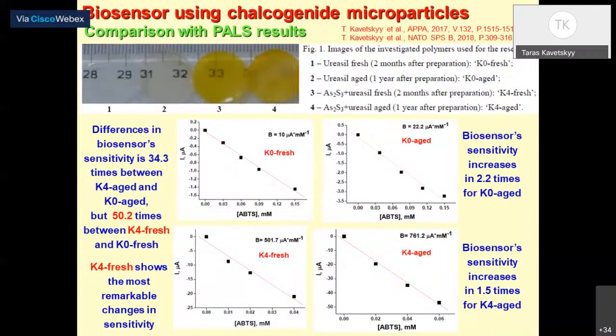But it is interesting to analyze biosensor parameters. When we compare the K0 fresh and aged sample, this is the pure Brazil matrix, we see that biosensor sensitivity increases 2 times after 1 year of aging after preparation. Also the same when we compare the K4 sample with chalcogenide clusters, we see that about 2 times biosensor sensitivity is larger for this aged sample. But when we compare the K0 aged sample with the K4 aged sample, we have a 40 times change in sensitivity, larger for the K4 aged sample. But when we compare the K0 fresh sample and the K4 fresh sample, we have an increase in sensitivity of 50 times. So the K4 fresh sample shows the most remarkable changes in the sensitivity of biosensors.